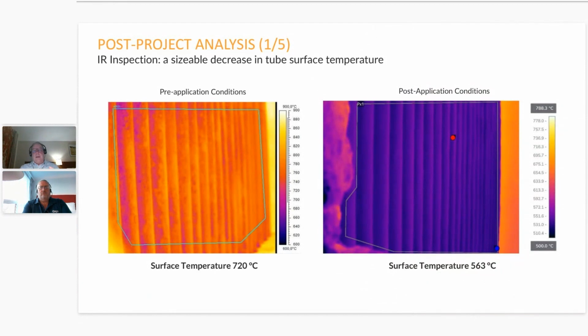Now here's the best part of this relationship. We had all this preliminary data, for instance, the first infrared image on the left, they're running that unit at 720 C. That starts to become problematic, and certainly those numbers can go up. You're also thinking about what's my actual tube metal temperature, looking at the tube surface temperature, and now we pivot over to what the coating did.